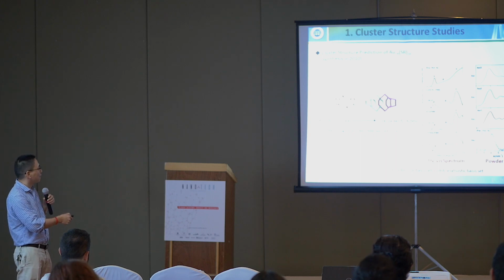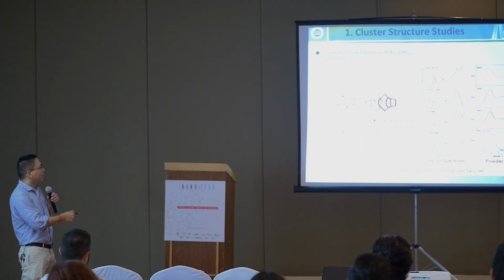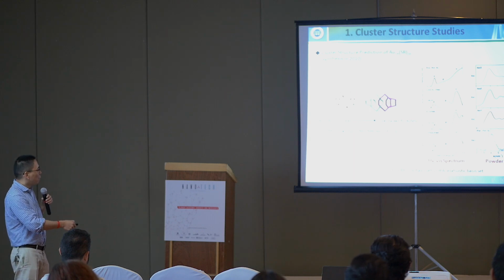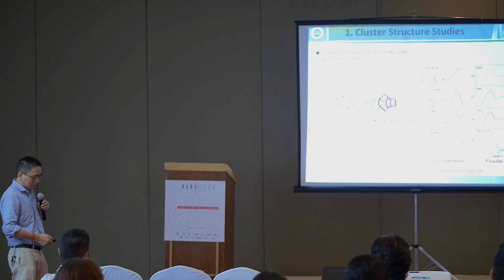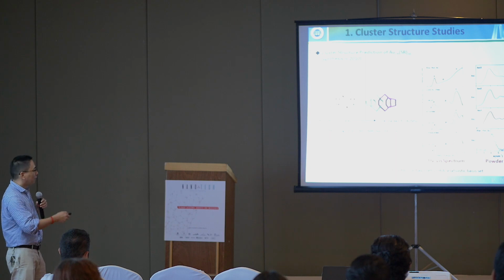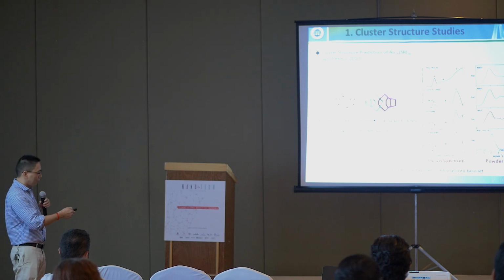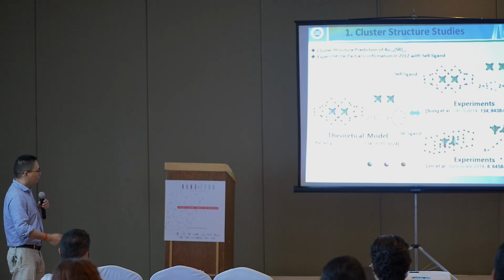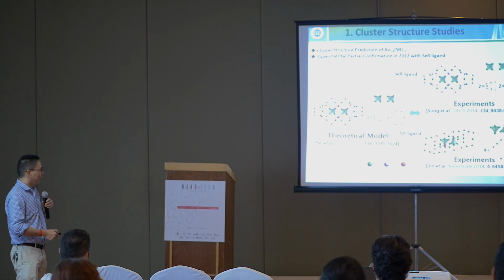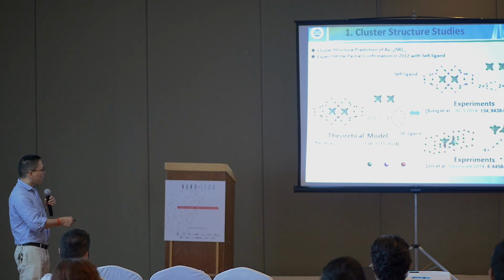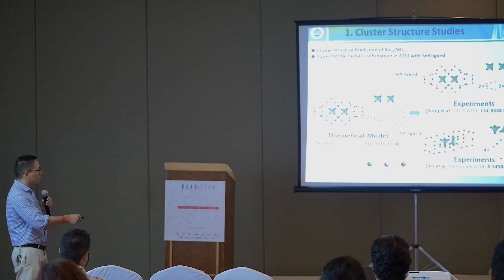This cluster was synthesized in 2010. And here is the comparison of the UV-Vis spectrum predicted from theory and the experiment. And the right is the powder X-ray diffraction curves. But unfortunately, there is a surprise. After our theoretical work, there are two experimental crystal structures.